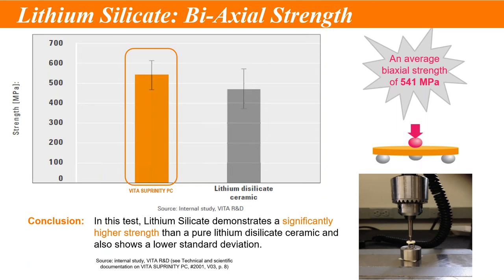Again, what we're used to for the strength, the conversation really has been around how strong is it under a standard bar that is bent and fractures. And that's really what the numbers are market-wise. They report biaxial or three-point bending in megapascals, not newtons, but megapascals, which is basically a set specific geometry. In this case, a biaxial is like a disc about the size of a quarter, and it's a certain thickness, and an apparatus just loads it until it fractures, and that's what the strength is.